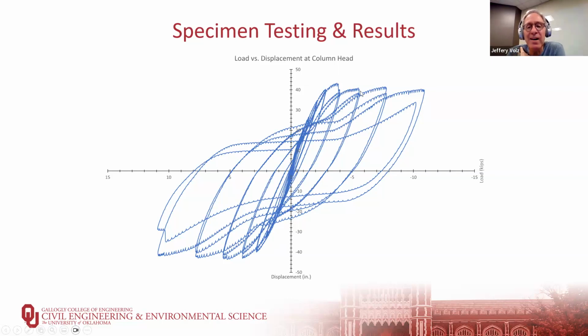What's happening here is, remember, we have that steel tube, which has a tendency to buckle locally. The concrete core is providing resistance to that steel tube. And we'll talk more about how it actually provides that resistance and the particular mechanics of it later. But just realize that at some point, that steel tube at the extreme fibers is going to experience a high enough strain that it wants to buckle locally. And that is what's happening here.